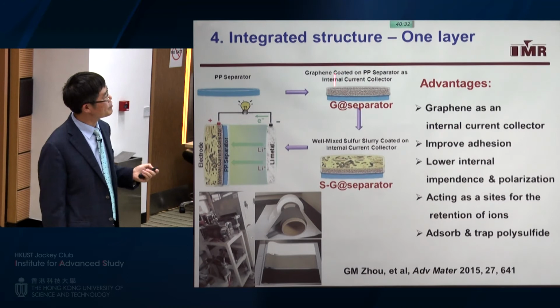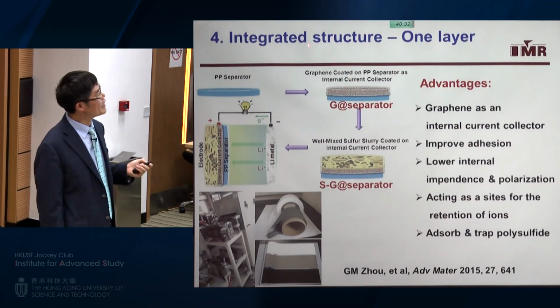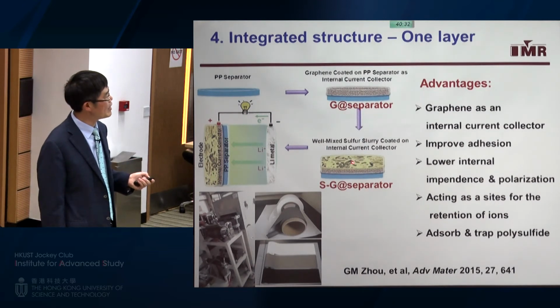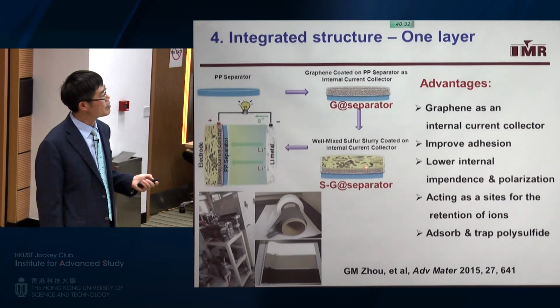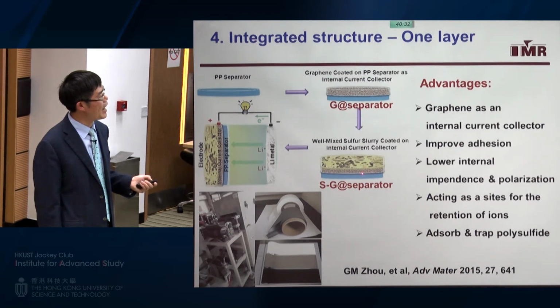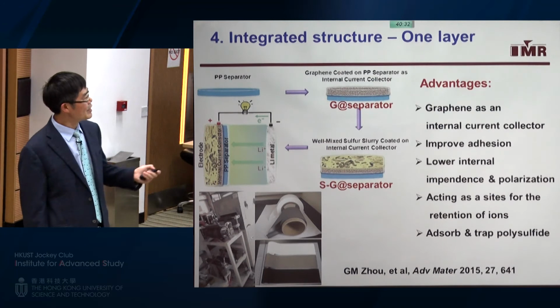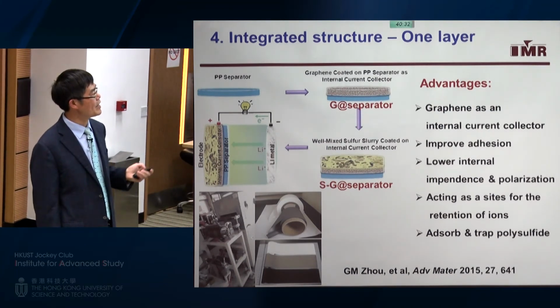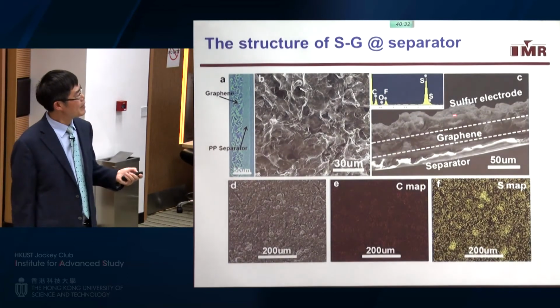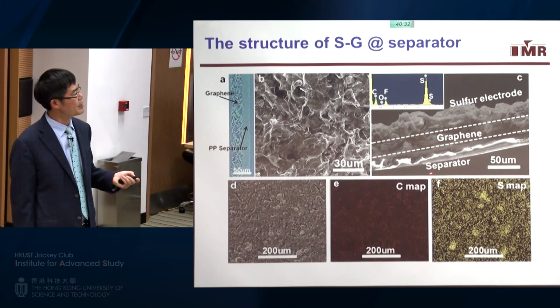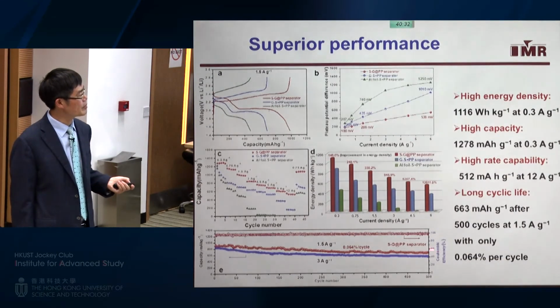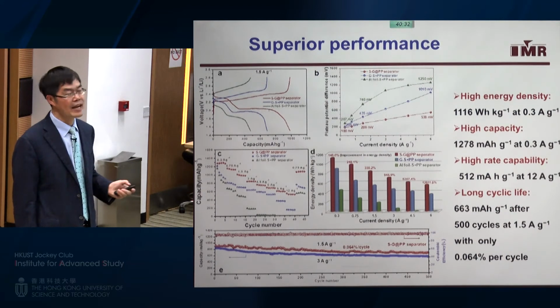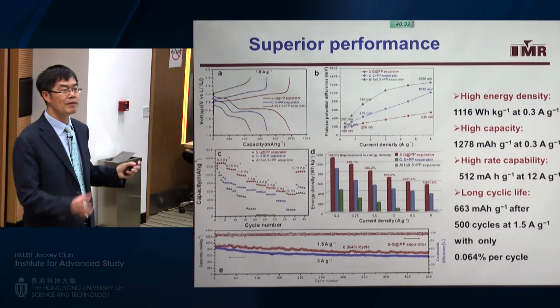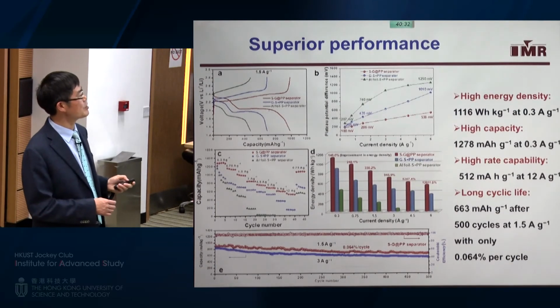We went one step further. So we incorporate the two layers into one layer. This is our integrated structure, one layer structure. We have this active material, we have this graphene layer, and we have the separator. So the graphene layer can be used as current collector and buffer layer. Actually the functions are very similar to what I just showed you, so I will skip. So you can see we have the three-layer structure: sulfur electrode, graphene, separator. And again, we have very good electrochemical performance, very nice cyclability even for 500 cycles. This is a very long cycle life for lithium sulfur battery.